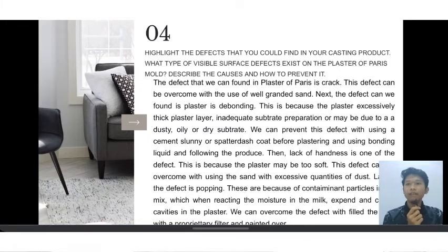Next, the defect that can be found is plaster debonding. It is because of an excessively thick plaster layer, inadequate substrate preparation, or maybe due to a dusty, oily or dry substrate. We can prevent this defect by using a cement slurry or spatterdash coat before plastering and using bonding liquid, or by following the process.